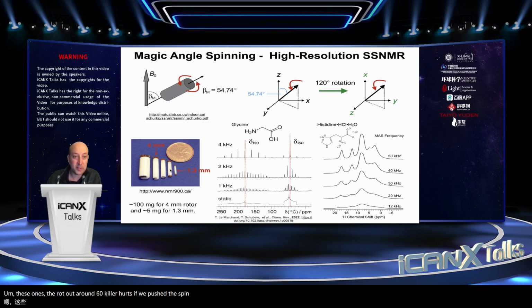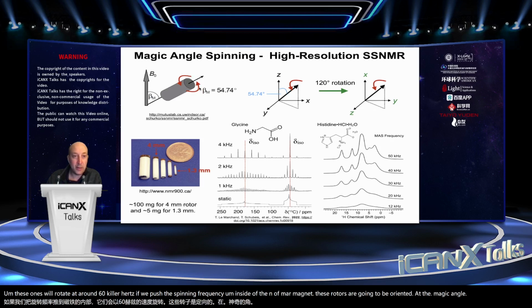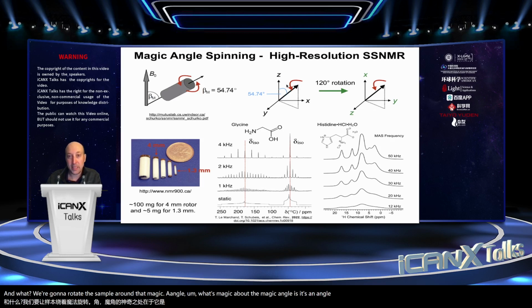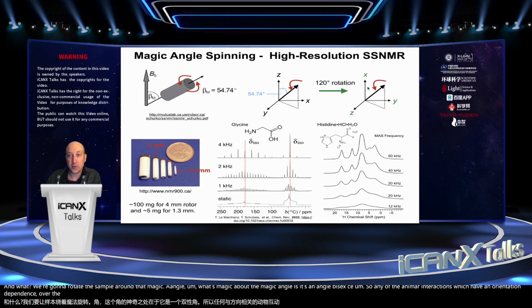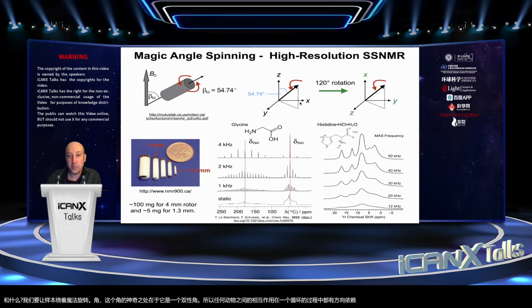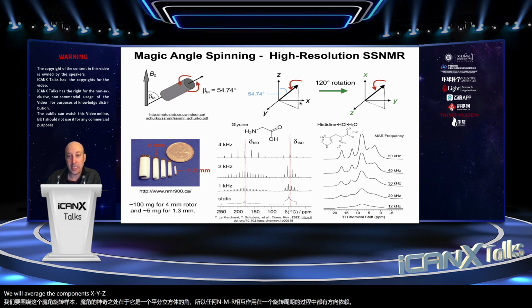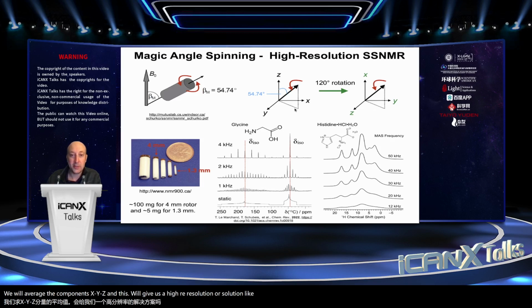Inside of the NMR magnet, these rotors are going to be oriented at the magic angle, and we're going to rotate the sample around that magic angle. What's magic about the magic angle is it's an angle that bisects a cube. So for any of the NMR interactions which have an orientation dependence, over the course of one cycle of rotation we will average the components X, Y, and Z, and this will give us a high resolution or solution-like solid-state NMR spectra. So that's just shown down here.